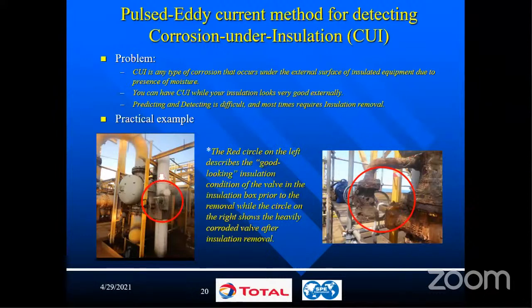I would talk a little bit about corrosion under insulation, because this is a bit of a headache in our industry. For sure, there is a need by process people and in the production system to have metallic or insulation jacketing in order to conserve or retain temperature. But this also creates a problem, because as soon as you have carbon steel operating between 60 and I think 120 or 140 degrees centigrade, insulated with water ingress, you are in the prime range of corrosion under insulation. And for stainless steels, it's even a bigger problem because you could have cracking in this type of environment, and when you have salt deposition in the water.